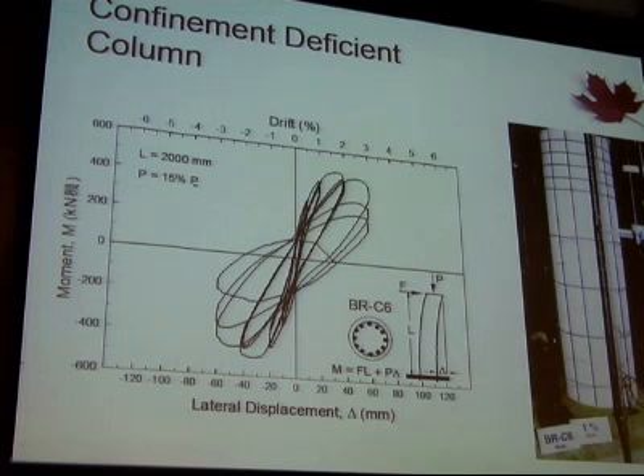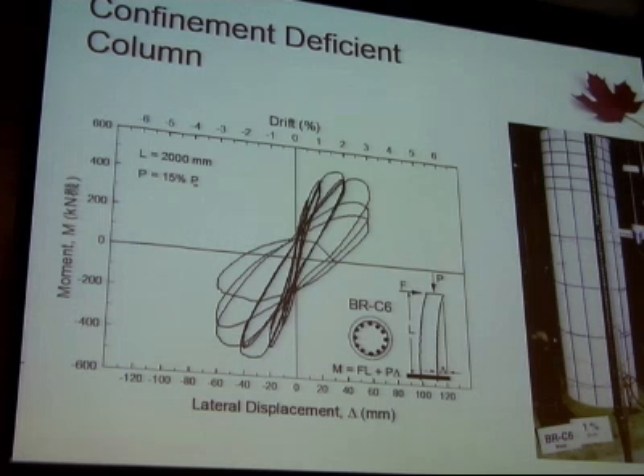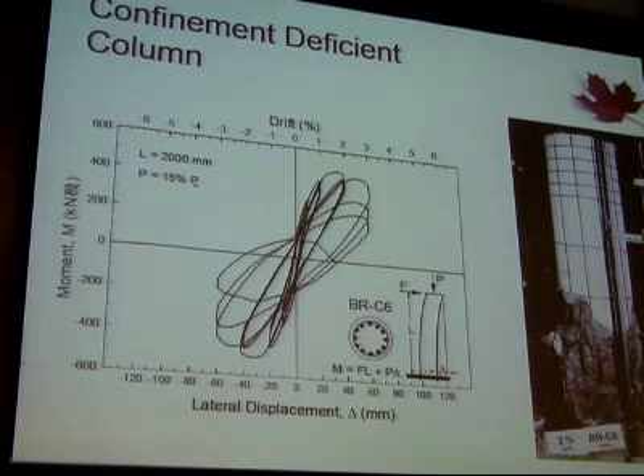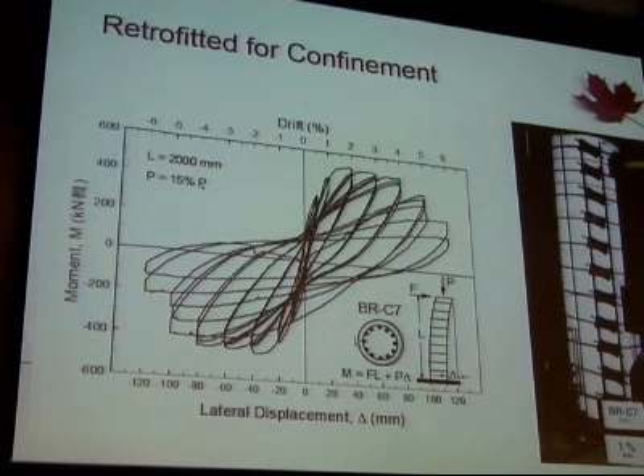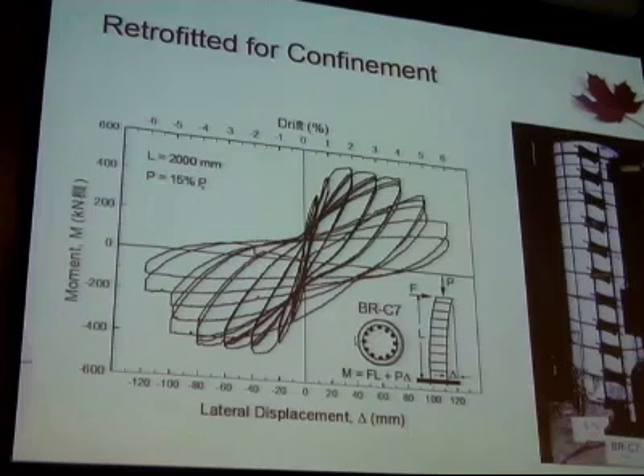Here's again a bridge column, this time a circular column, that was able to go up to 2% drift. Unlike what we think, reinforced concrete has inherent deformability, and this is an unconfined column being able to go up to 2% drift. But at that time, the cover started spalling off, and then the reinforcement rebar started buckling. But when we retrofit them with transverse pre-stressing, the performance improved, deformability went over 4% drift, and the damage on the column was extremely limited.